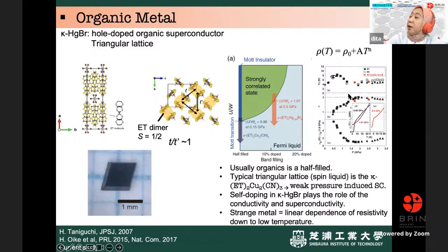For the resistivity, it has non-Fermi liquidity, because the N value here, the temperature dependence of the resistivity, is linear, and then by pressure it becomes 2. So here is the resistivity behavior from 1 to 2. Usually organic metals are half filled, one electron per site, and this one is a typical triangular lattice sample, which is kappa-(ET)2Cu2(CN)3. This is a weak pressure induced superconductor. I mean, this is insulating, but using a little bit of pressure, it becomes a superconductor.